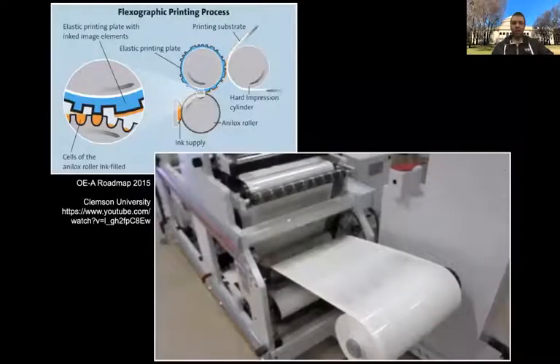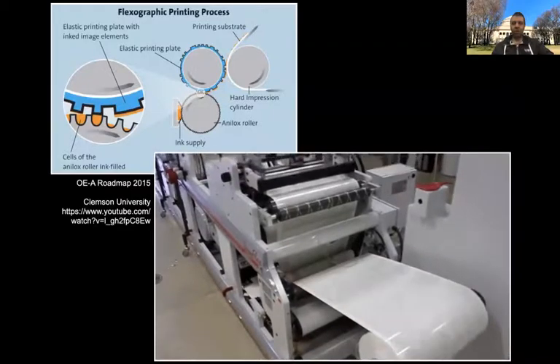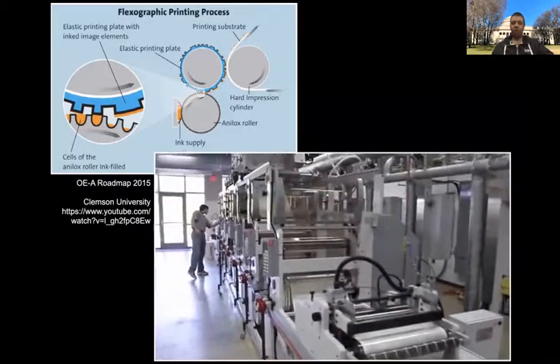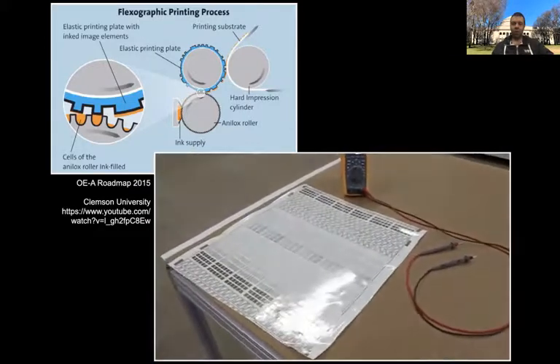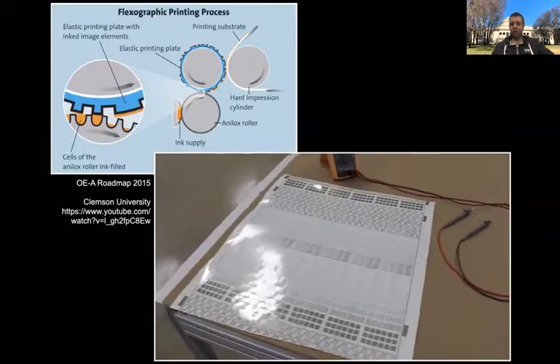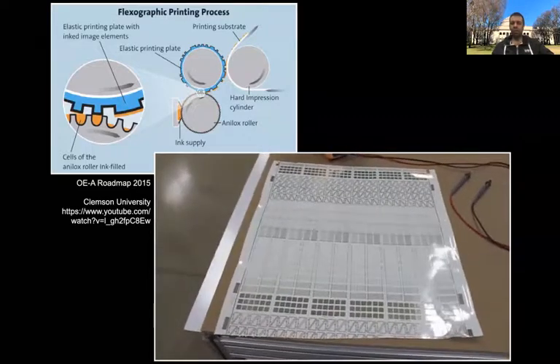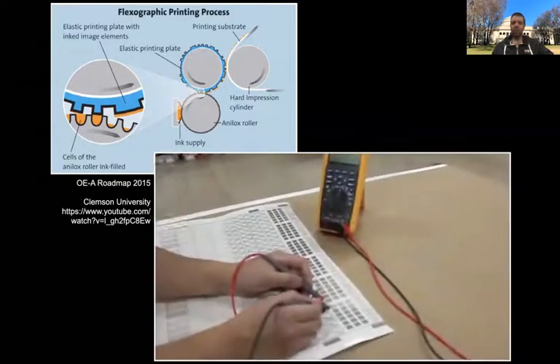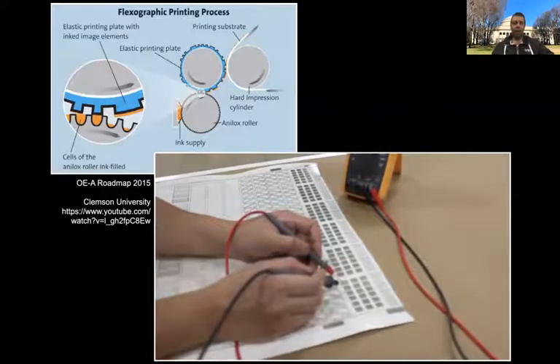And in the context of printing electronic materials, here's a sense of what's necessary to reach scale. This is a pilot line for doing flexography of a simple silver ink at a university in the US. And you saw the high speed. Hopefully the video is smooth, and that is an indication of the rate that you need. And that's just printing a sample conductive pattern here. The flexography process involves the motion of a roller with a raised stamp, and transfer of ink actually between 3 rollers, 2 steps of transfer: first a supply roller onto the stamp, and then second the actual print roller, where you print onto the typically flexible substrate. Here it's an engineered paper.